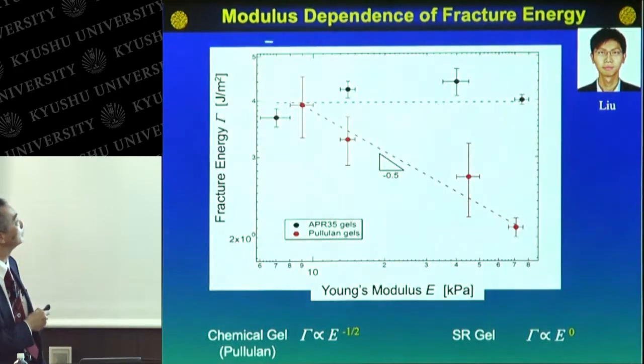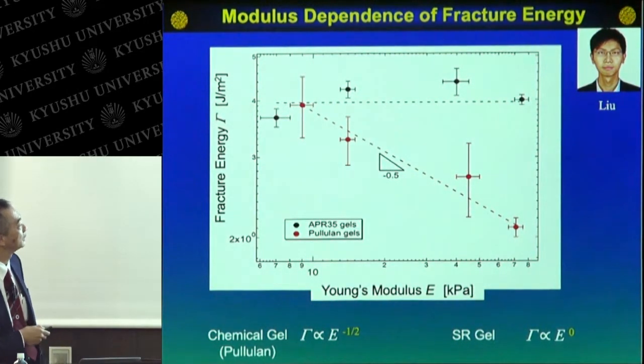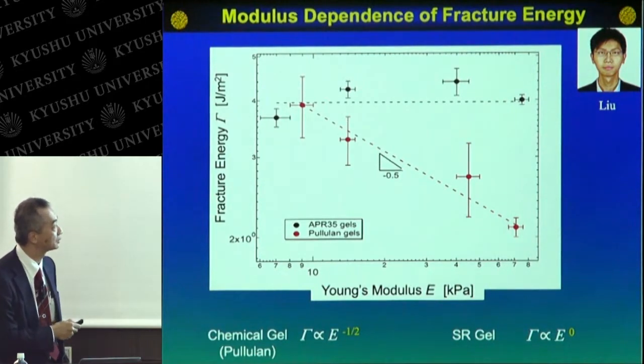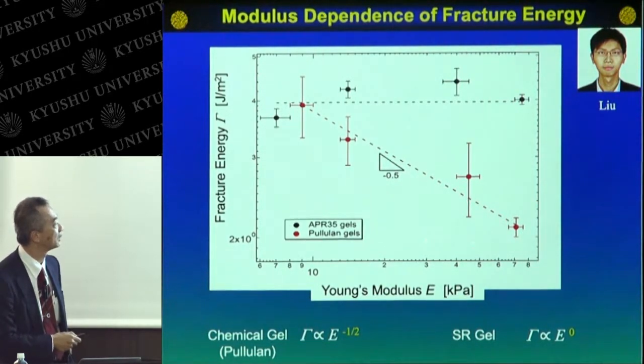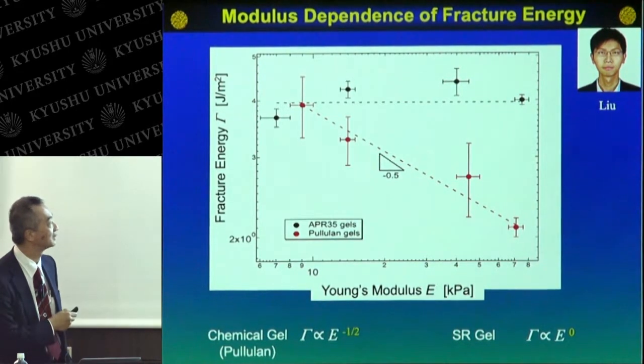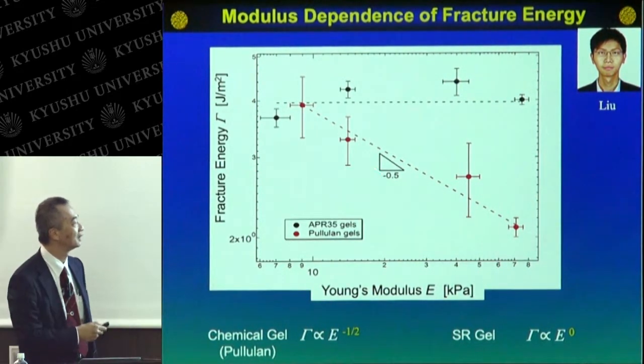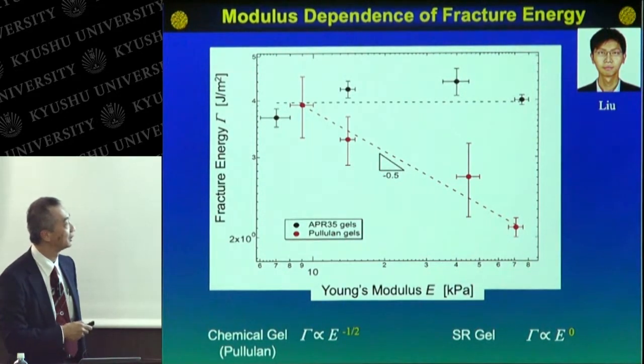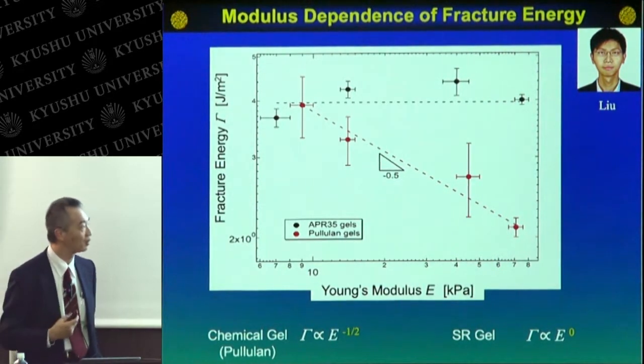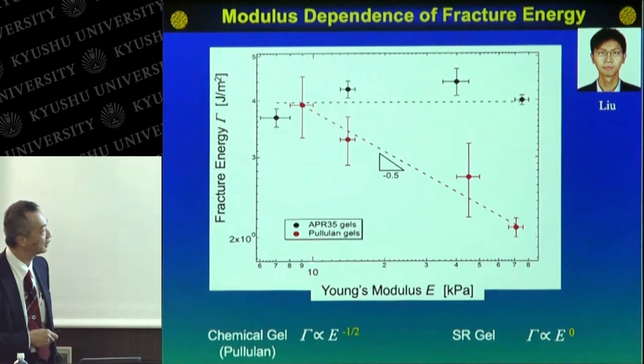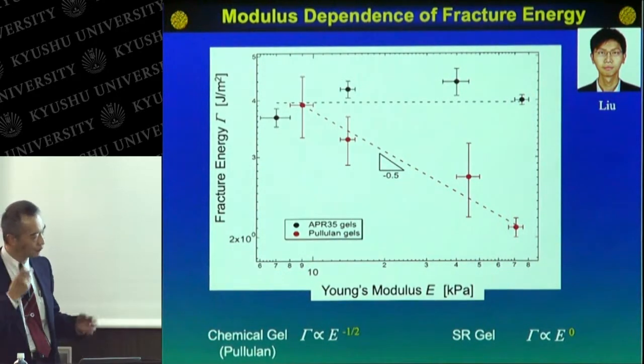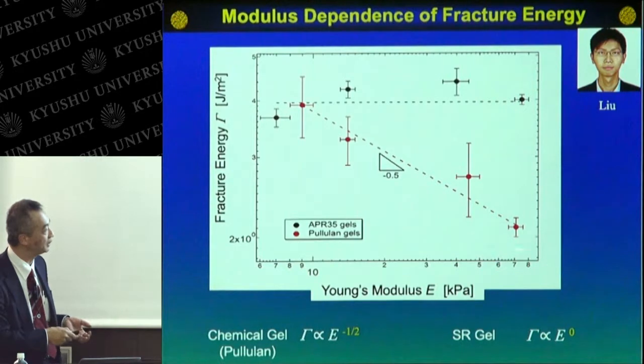This shows the modulus dependence of the fracture energy. Usual chemically cross-linked materials show a decreasing dependence of the fracture energy on the Young's modulus. And this behavior is well explained by the Lake-Thomas theory. So when the polymer chains are cross-linked more densely, the fracture energy decreases drastically, like this.